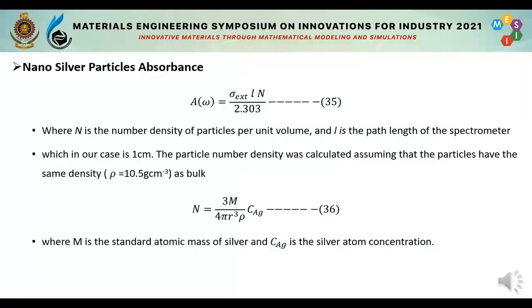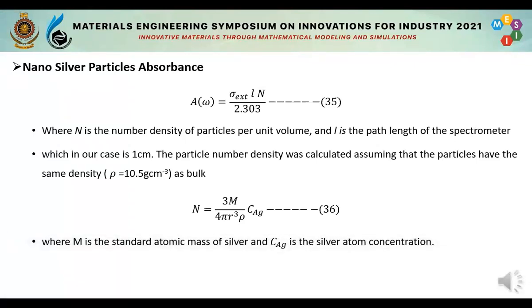If the silver nanoparticles are dispersed in a homogeneous medium and the interparticle interactions are negligible, then the extinction cross-section can be modeled as the optical response of one immersed nanoparticle times the particle number density. The extinction is the sum of the absorption and scattering cross-sections of a single particle. The calculated extinction coefficient can be mapped to the experimentally observed absorption for a dilute spherical nanoparticle dispersion, and the number density of particles per unit volume is needed to calculate the total absorbance value in solution.